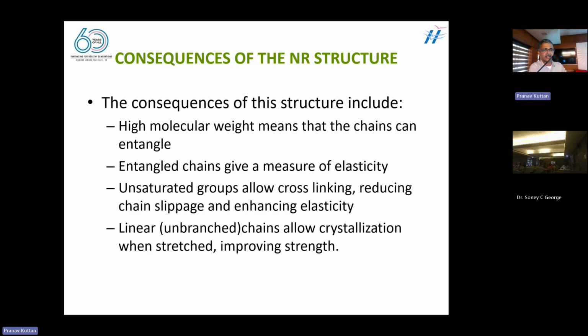So what is the structure telling us? The high molecular weight means that the chains in a small area will entangle as a network structure, like you can see in pasta noodles, which form a chain entanglement structure. So it gives a measure of elasticity to the molecule. As you might have seen from your school days, the rubber bands which are used are elastic. The elasticity is given by a process called vulcanization, in which the chains are cross-linked by using some molecules, especially sulfur.